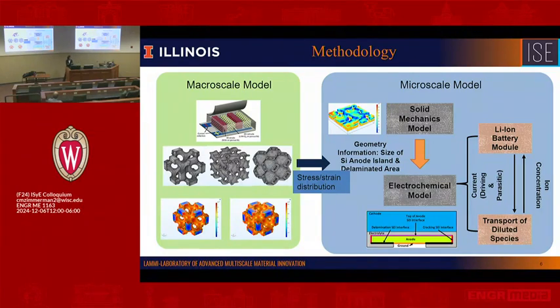So this illustrates the general platform of the multi-scale models we developed. For the macro-scale model, the major feature we carry is the 3D structure, and we investigate how the 3D structure impacts the stress distribution within the electrode under different operation conditions, like temperature and charging rate. With that information collected, we can pass it to the micro-scale model. For the micro-scale model, we use a rather simplified representative volume model, which is only one thin layer of silicon on top of the substrate. The substrate will usually be metal.